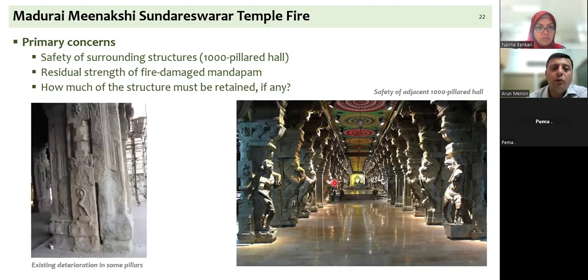And there was a multidisciplinary group, as stated earlier, which was trying to understand what can be done. But the concern also was that the stone in this particular structure had seen a lot of deterioration over time. Not all of the stones, but some of the pillars had seen a lot of deterioration. You can see that the sculptural quality was lost because of the surface deterioration in some of the pillars.